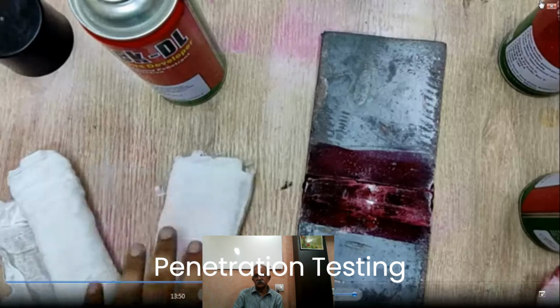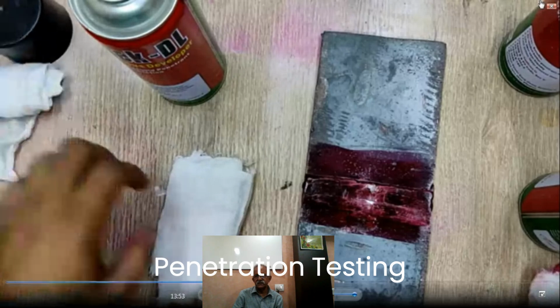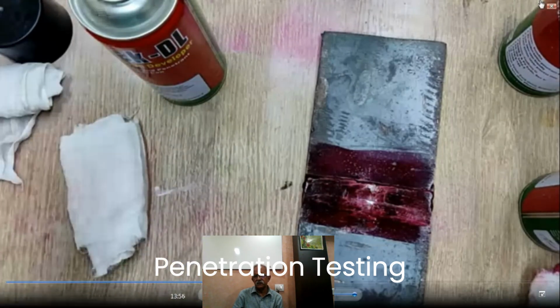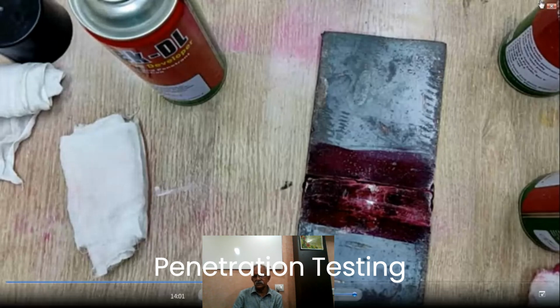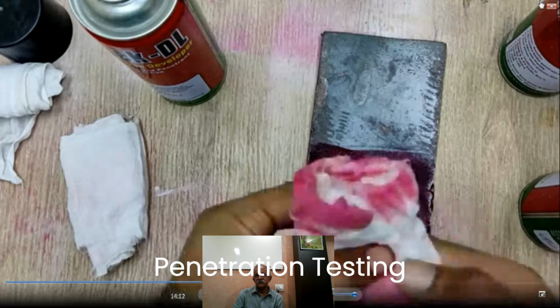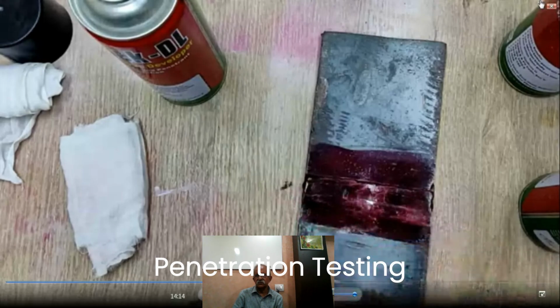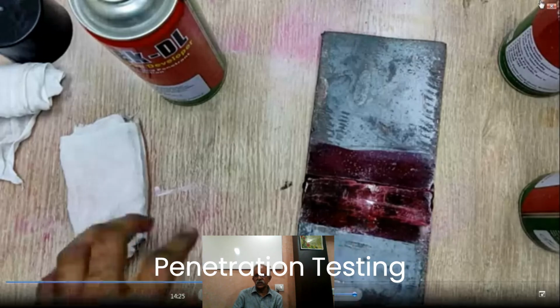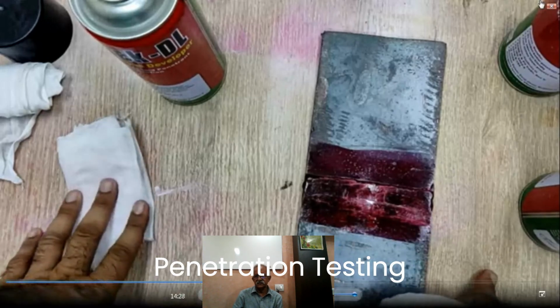But generally, our dwell time is 10 to 15 minutes. 10 minutes is a standard that is being followed across the world. So that sort of dwell time you can keep, so that the capillary action takes place completely, and we find out the amount of flaw that actually goes into the welding, so that it actually shows the defects.